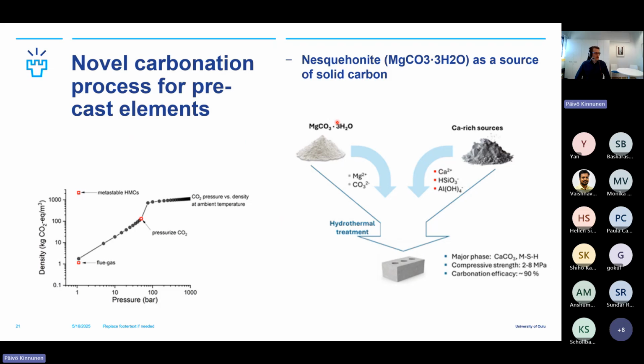So here I want to introduce you to a novel carbonation process for precast elements. We are taking nesquehonite, which is a type of magnesium carbonate with some crystal water. Here's the equation for that, and basically this is the source of magnesium and the source of carbonate. And then what we took here is calcium-rich sources, which contain calcium, silicate, and also some aluminate.